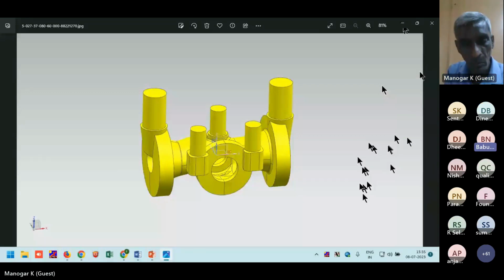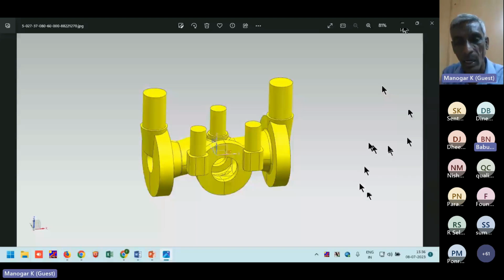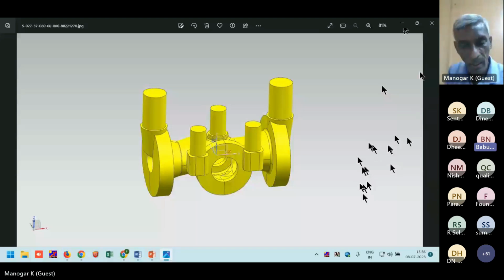As per our knowledge, exothermic sleeve will not give 60% feeding efficiency. Yes, practically it is not giving. That's what I mentioned. You should make your own standard and confirm with the cube test. As per our knowledge, and a lot of people are here also from methoding, an exothermic sleeve is giving feeding capacity not more than 35 to 40%. Sir, it is working up to 40-45%, it is giving with a branded sleeve. Yes, sir, you can take branded in the market, it is not more than 35 to 40%.